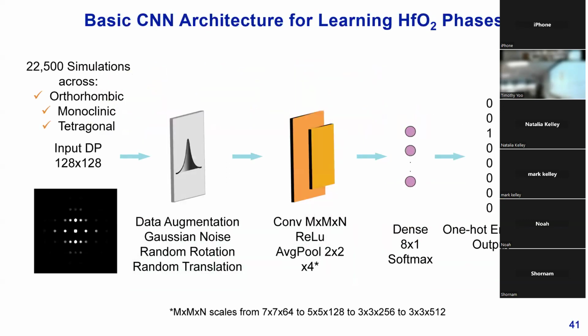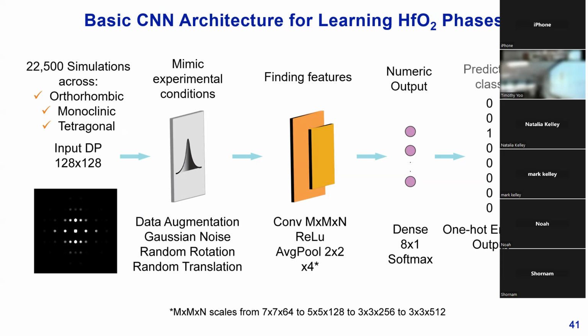And so here's what we're going to call our basic convolutional neural network model to start off with. In the beginning, we've generated 22,500 simulations of 3 different phases of hafnium oxide, the orthorhombic, monoclinic, and tetragonal, as we just saw. And this input data is going to be run through a data augmentation process, which is essentially going to mimic your experimental conditions. This is going to be things like Gaussian noise and random rotations and translations between your patterns. And then we're going to send it through convolutional filters, which are essentially finding key features that describe your data set. This is again going to lead to your numeric output, which is then going to be translated into your final predicted class. In this case, what phase does that diffraction pattern belong to?